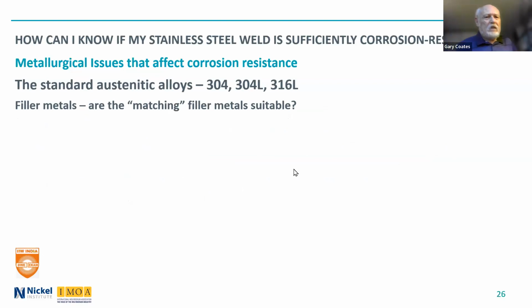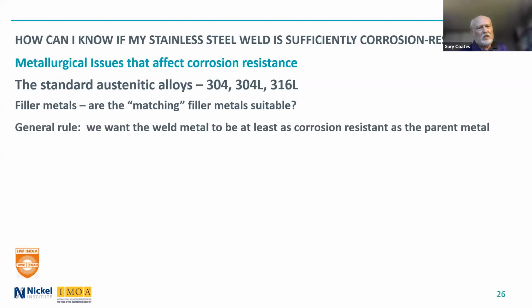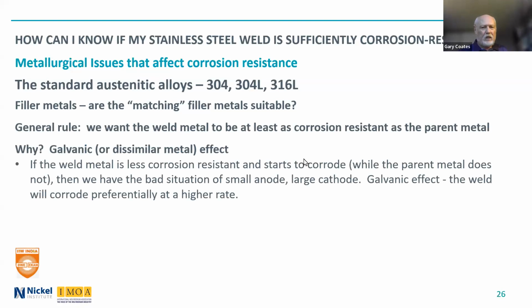So let's talk about the standard austenitic alloys, 304, 304L, 316L. Are the matching filler metals suitable? First of all, as a general rule, we want the weld metal to be at least as corrosion resistant as the parent material. Why is that? Well, the old galvanic or dissimilar metal effect. If the weld metal, which is a small area, is less corrosion resistant and starts to corrode, while the parent material does not, we have the bad situation of small anode, large cathode. So you have at least a potential for a galvanic effect there.